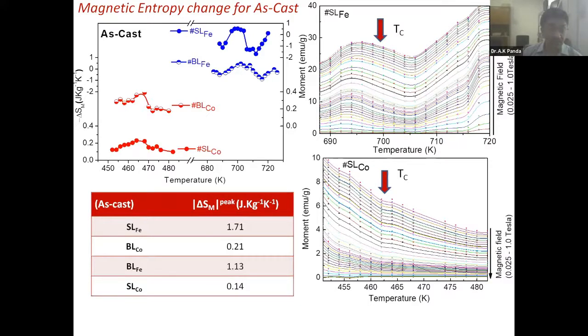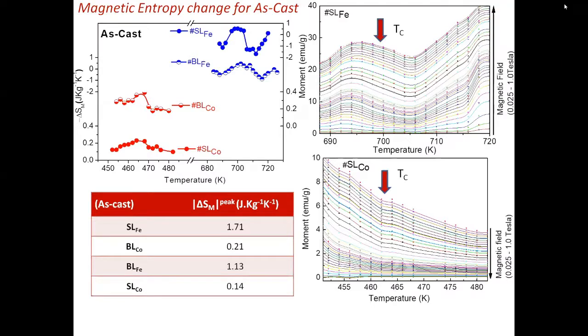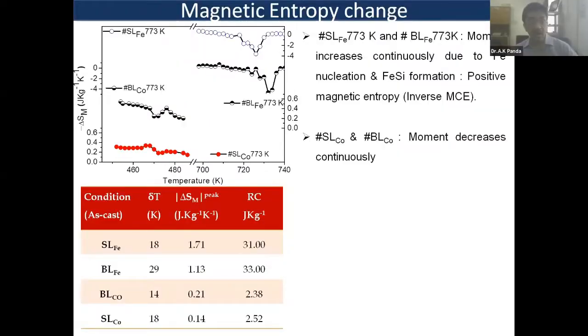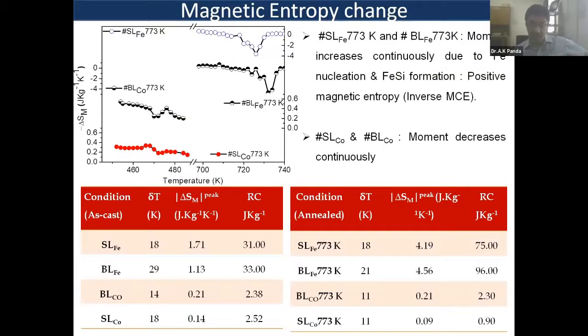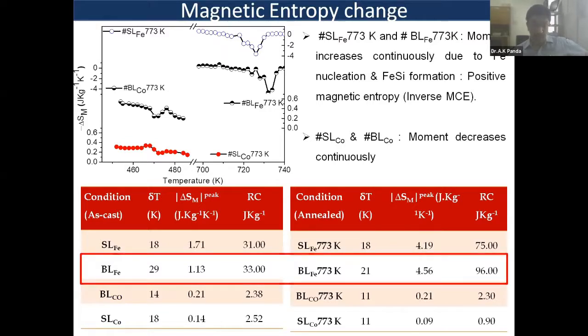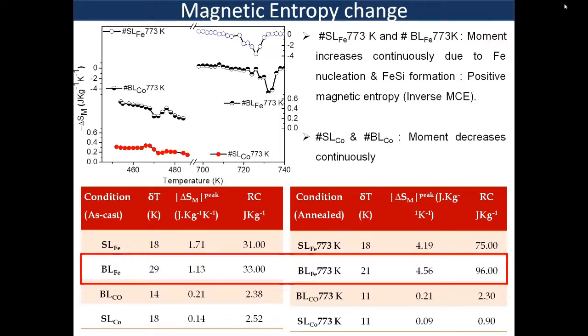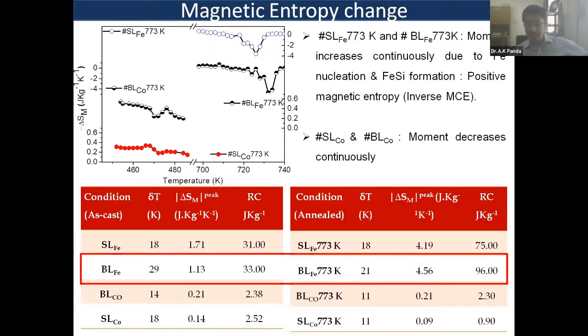Of course, these are not very interesting in terms of your nickel manganese gallium alloy, but certainly you need much lower field. These have been measured at around 1.2 Tesla compared to 3 Tesla. So there is an advantage that you can go for. So I will move fast to the comparison. This is the one bilayered ribbon. For the bilayered ribbon, you can go to delta, and this is how you can get a relative cooling capacity of about 96 joules per kilogram.